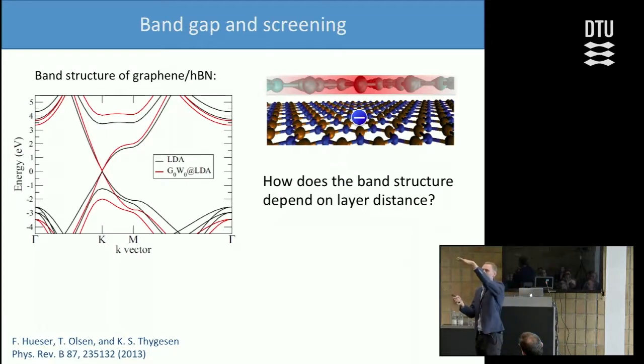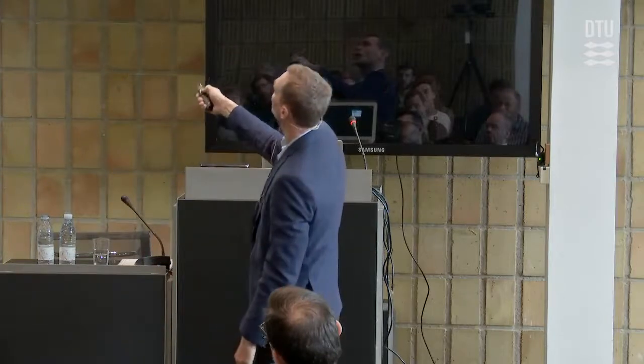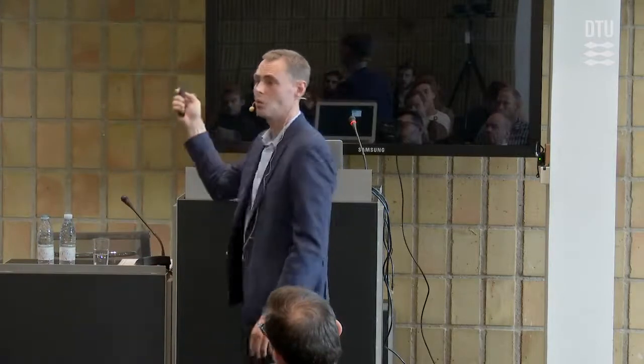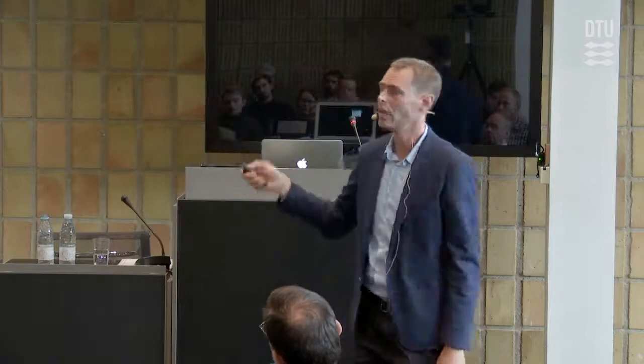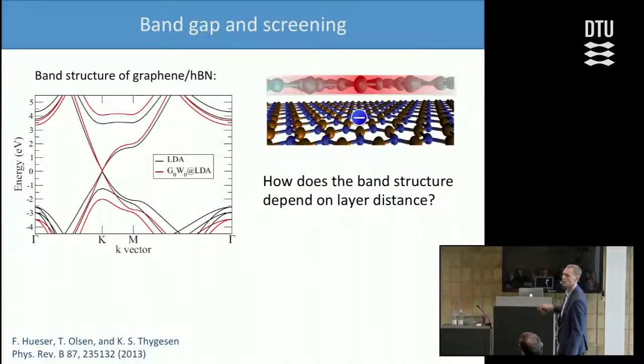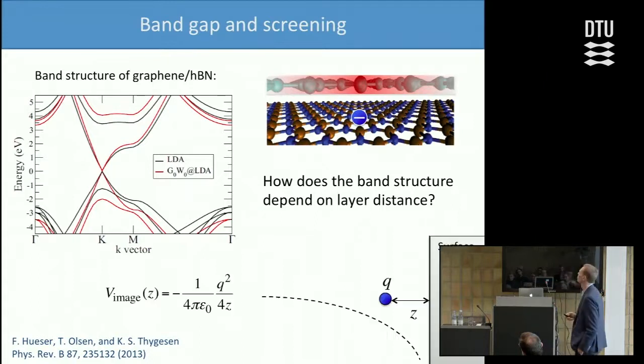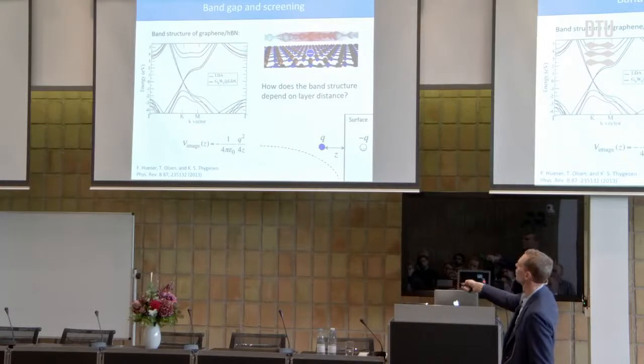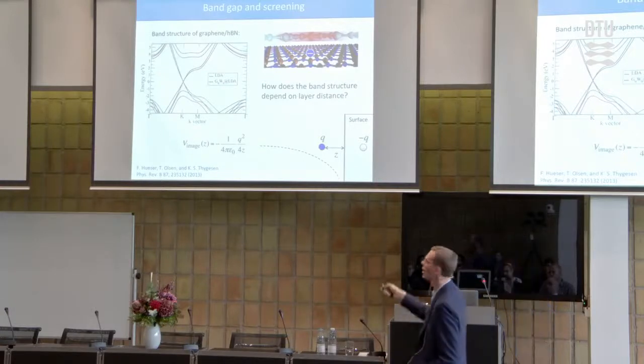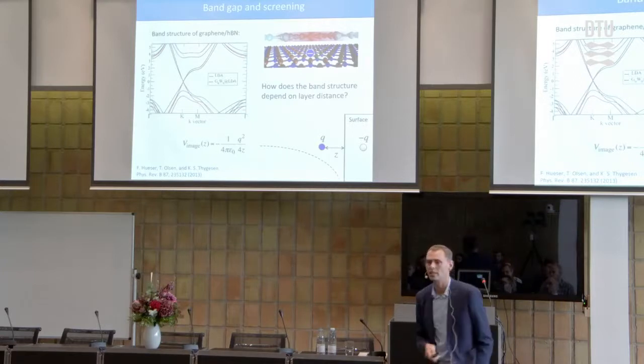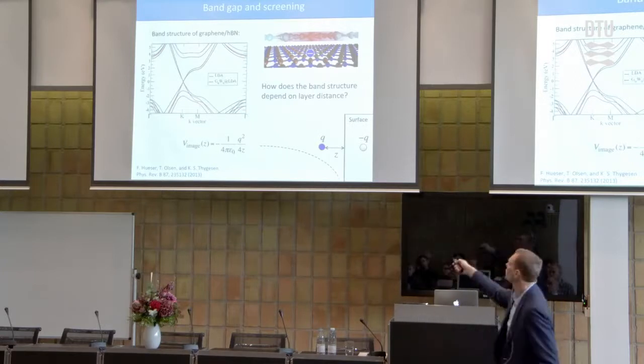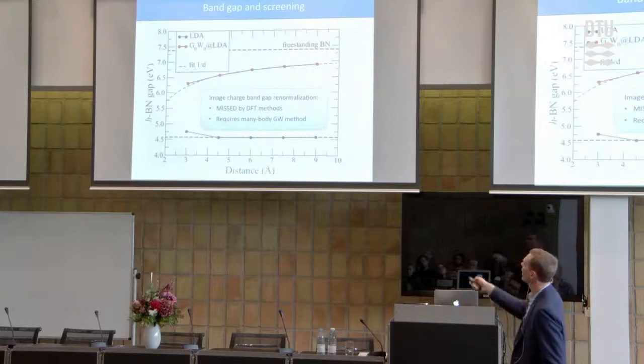But now there is a graphene layer on top. That negatively charged electron will induce a positively charged image charge in the graphene layer, and there will be a positive interaction between the two. That's a correlation effect we have to take into account. In the simplest classical description, we could use an image charge model, and then we would expect a 1-over-distance dependence of the band gap in hexagonal boron nitride, dependent on the distance to the graphene. That's exactly what we find.